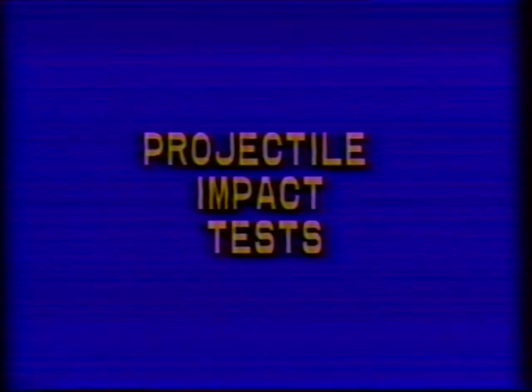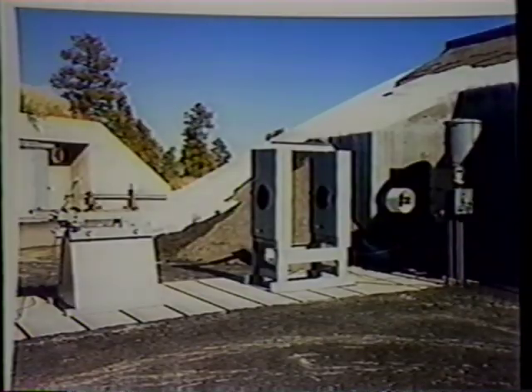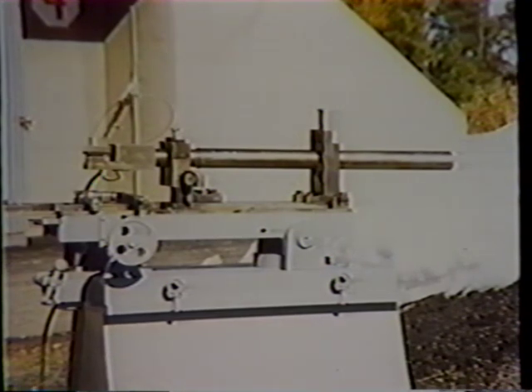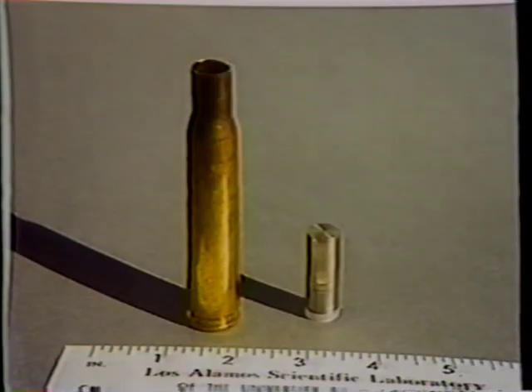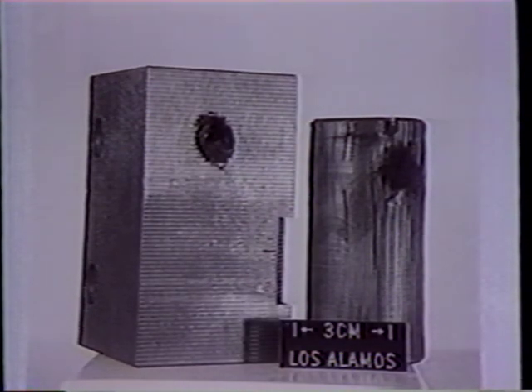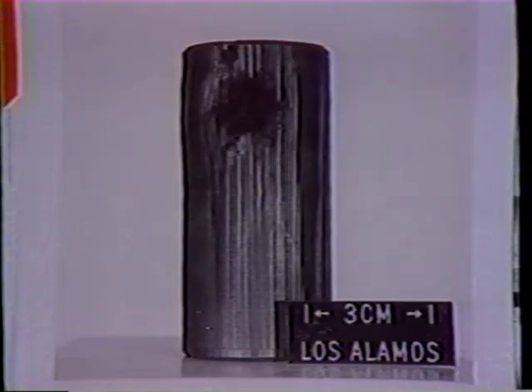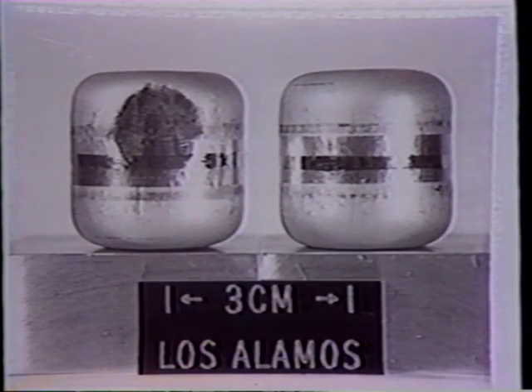A total of 20 projectile impact tests used 3 types of projectiles and 4 different targets. These tests were designed to span the range of probable projectile velocities associated with a launch vehicle explosion. Initially, 50 caliber aluminum bullets and 30 caliber titanium bullets were fired into heat source modules and fuel capsules to test the response of the heat source to collisions with small projectiles. These tests showed that the threshold for direct mechanical damage of a fuel capsule ranged from almost 1,400 feet per second to more than 1,800 feet per second, well beyond the projectile velocities predicted for a Titan Centaur explosion.